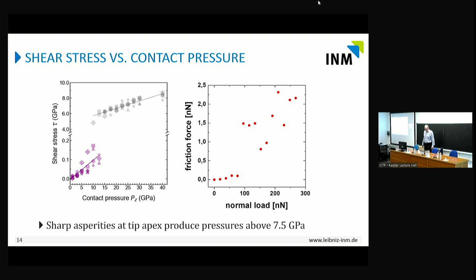And so if you summarize this, here you see results for 5 simulations, for 5 different configurations of the silicon oxide tip. And you can see we have a more or less linear regime at low pressure, where we have something that I assign as a Prandtl-Tomlinson type thing. It's purely elastic, and it's just relaxation of some elastic energy. And then we have a sudden transition, but actually in the transition regime between 7.5 and 12 gigapascal, it often jumps up and down. So we have a lot of chaotic back and forth of configurations, plastic events in the silicon oxide, and that is actually, I believe, what gives us in the tip this large scatter in the friction force values.